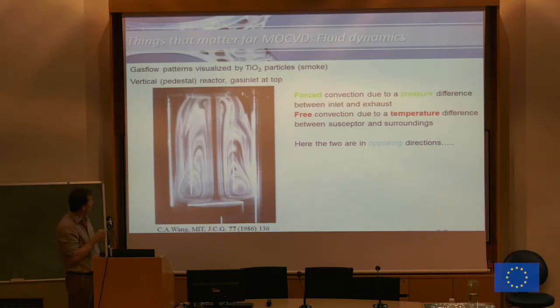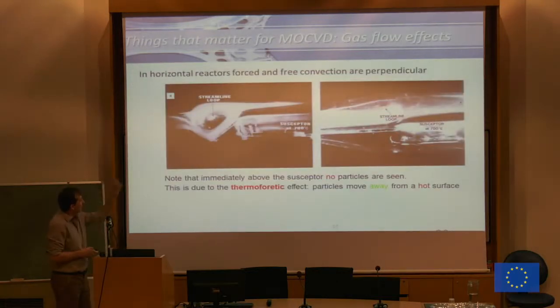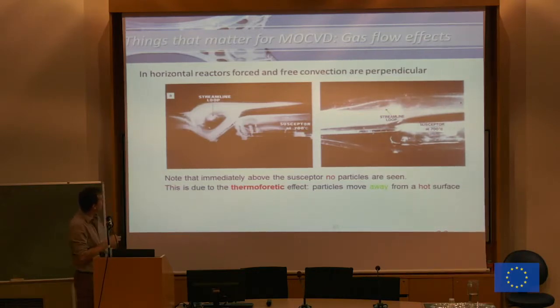And because you have two opposing forces, namely the forced convection down and then the convection because of the temperature difference up, you get these very funny flow patterns in your reactor. Needless to say that this is not a commercial model of reactor. Now what I really wanted to show is this plot here where they in fact do the same thing. So it's a horizontal reactor now. The susceptor is this block here, it is heated. And the gas is introduced from the left to the right.